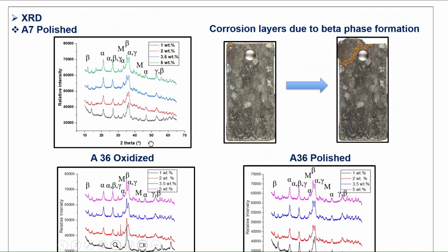Coming to the XRD, we can see the presence of the beta peak, and this peak also increases in size with increase in the salt concentration. And even in the case of alpha, the alpha is growing with increase in the salt concentration.